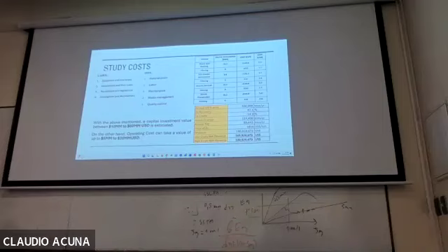And again, you have the total solid tons per hour, and then you guess a number. Solid content can't be that bad: 20%, 30%, 40% is usual for leaching gold. I'll put 20. If I put 40 it will not work, you already know that. Let's take 20, we know it's not a real case. And then the residence time, K value, we don't know.